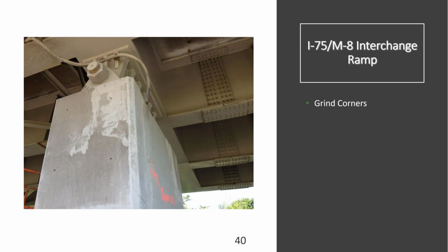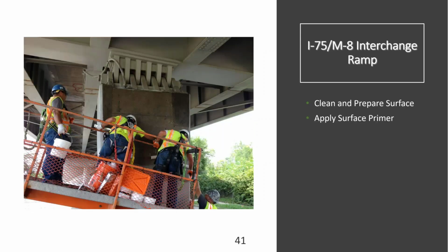In order to finish the concrete surface preparation, the surface needs to first be sandblasted to a minimum ICRI surface profile of CSP3. Basically, that is just removing all dust, dirt, bond-inhibiting compounds such as oils. And then after preparing the substrate with a light sandblast, what we see here in the picture is we're applying the first epoxy that gets applied, and this is the primer.